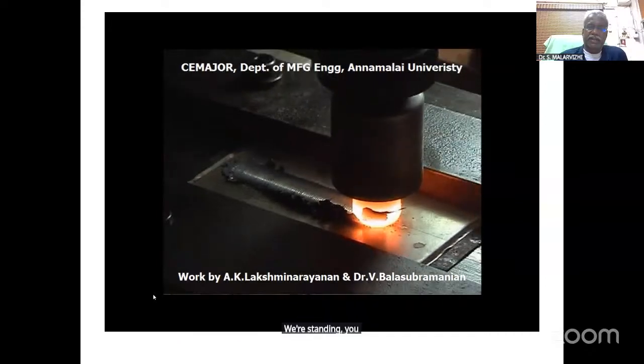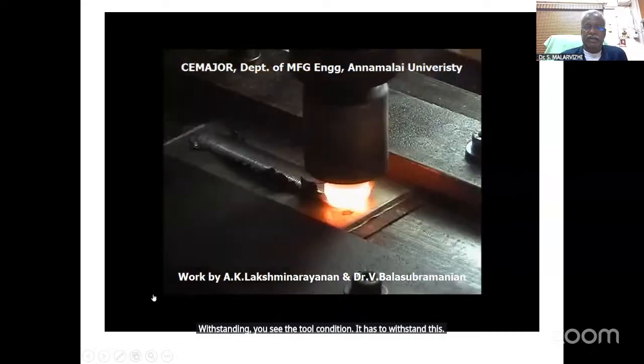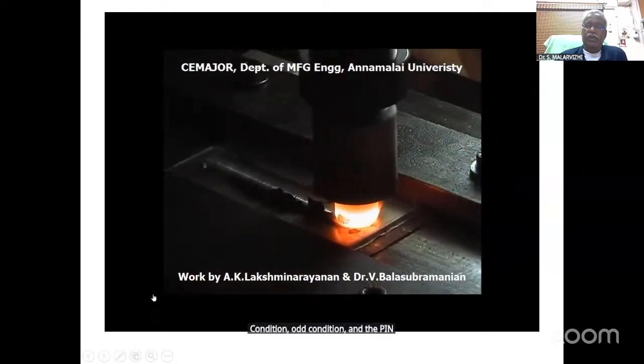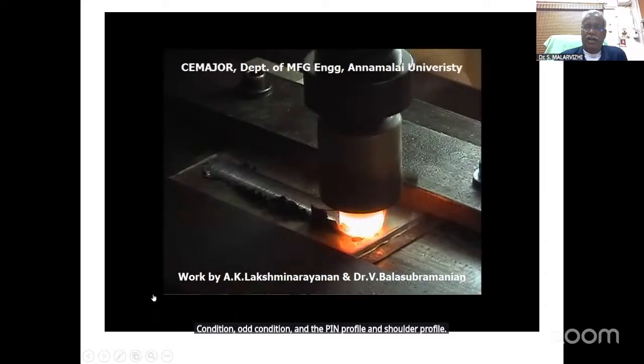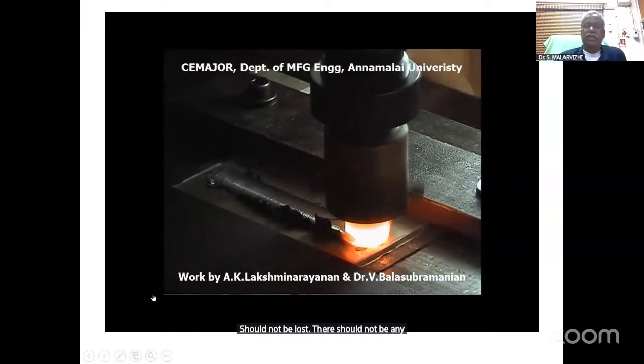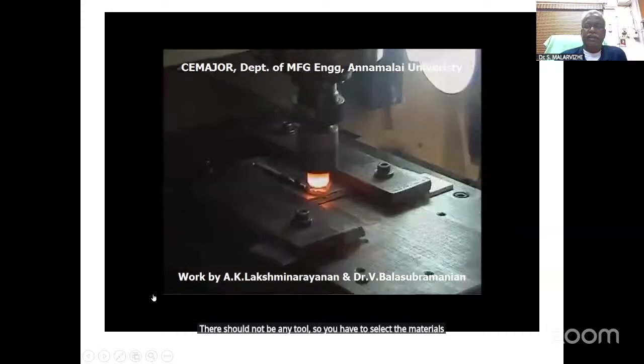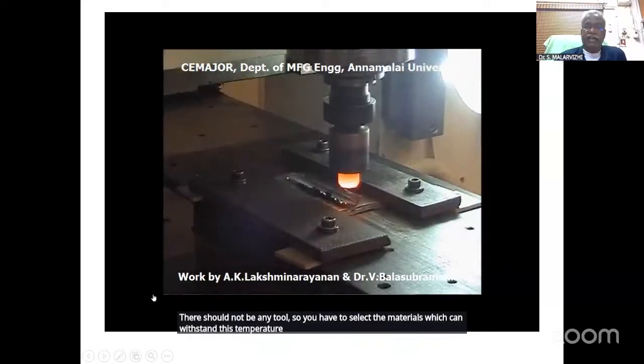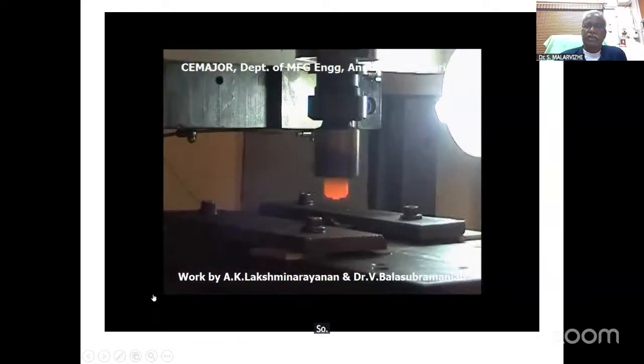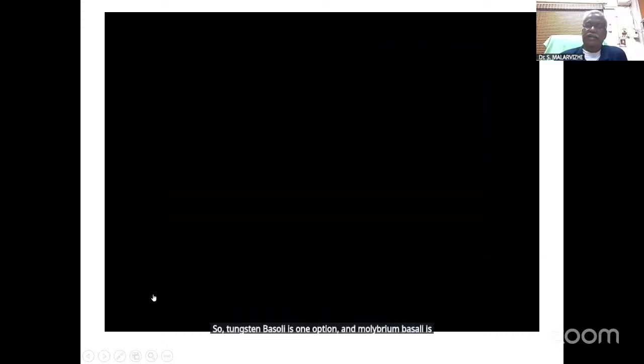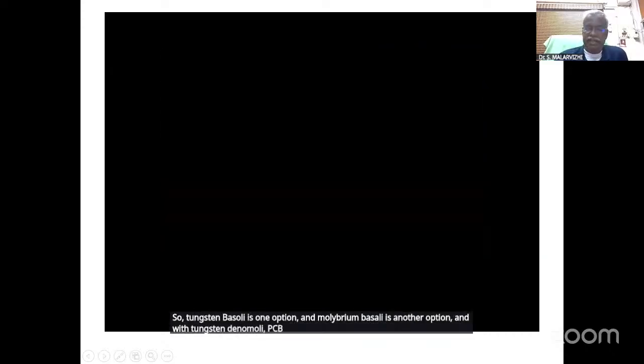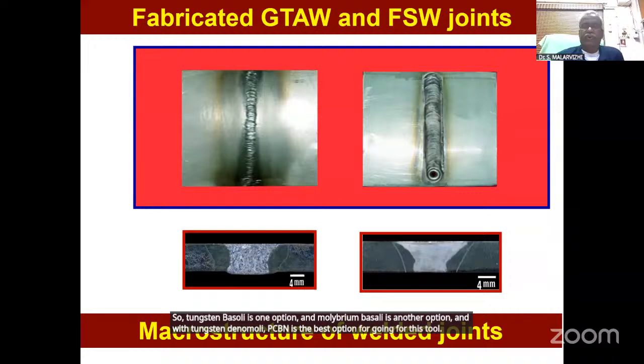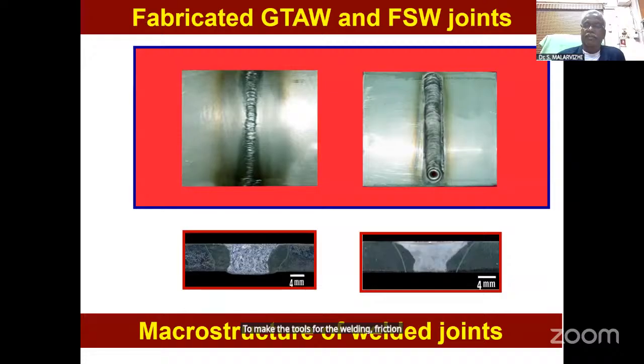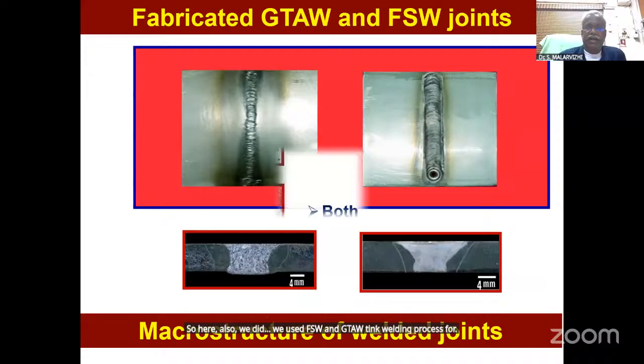withstanding, you see the tool condition, it has to withstand this hot condition. And the pin profile and shoulder profile should not be lost. There should not be any tool wear. So you have to select materials which can withstand this temperature and also the forces at this temperature. Tungsten-based alloy is one option, molybdenum-based alloy is another option, and tungsten rhenium alloy, PCBN is the best option to make the tools for friction stir welding of high melting temperature materials. So here also we used FSW and GTAW TIG welding process for joining IF steel.